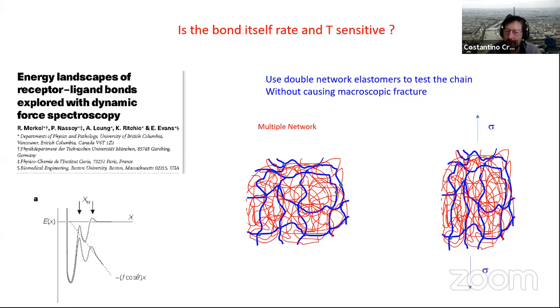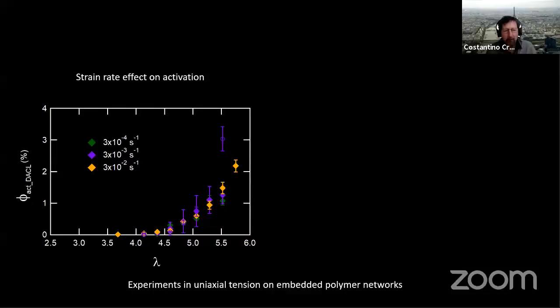But in our experiment, we see the exact opposite. When we go to high temperature, we break fewer bonds. So obviously this is not the full story, but we should do a cleaner experiment. So what we did is we took our network and embedded it into a stretchable matrix. Now by pulling the stretchable matrix, you can load the polymer chains without breaking the sample. So you can actually do some statistics. We did these experiments, and here you're looking at the activation of mechanophore in these materials as a function of stretch. Again, these are the embedded materials for three different strain rates.